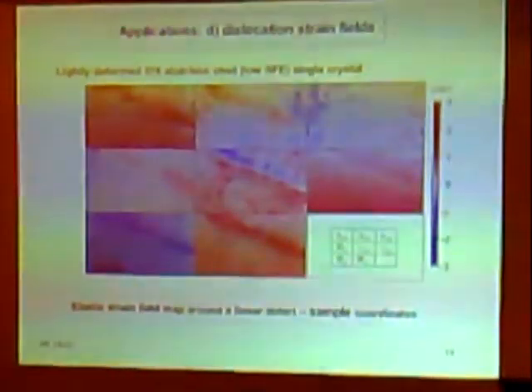This is a more recent observation. What I've shown you so far are either pure elastic strains or pure results of plastic strain, which are GNDs, but not elastic and plastic together, which is more difficult to do. Now this is an example of a low stacking fault energy stainless steel single crystal, scanned across here with high resolution EBSD, and we've got strain variations. This is epsilon 1,1, this is 1,2, 1,3, and rotations R3, R2, R1. And you can see there's a linear defect going across this sample.